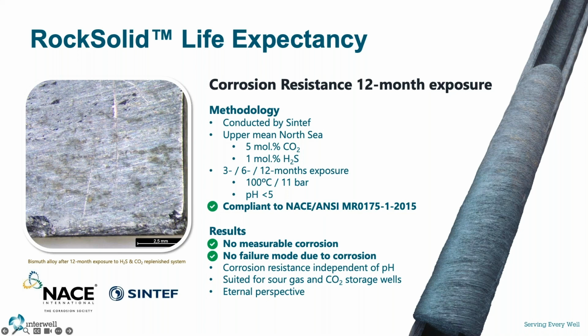So what I was saying is that 3, 6, and 12-month corrosion tests were conducted in a replenished system with 5% CO2, 1% H2S at 100 degrees Celsius and 11 bar pressure. At the end of the 12-month tests, it was determined that there was no visible, measurable corrosion and no failure mode due to corrosion. Sintef claimed that this barrier, for all intents and purposes, as far as testing is capable of going, can be deemed an eternal everlasting barrier. It won't break down, making this product suitable for sour gas, CO2 wells, CO2 storage systems, among others.